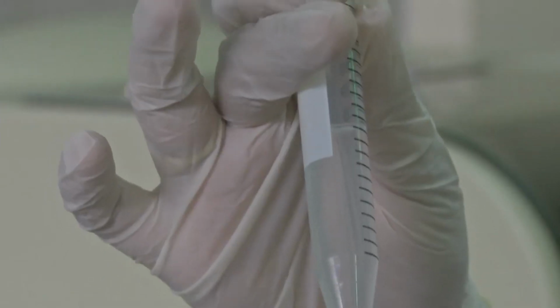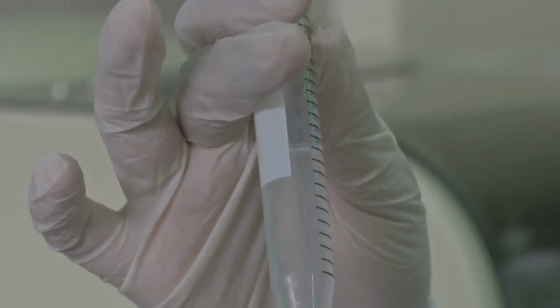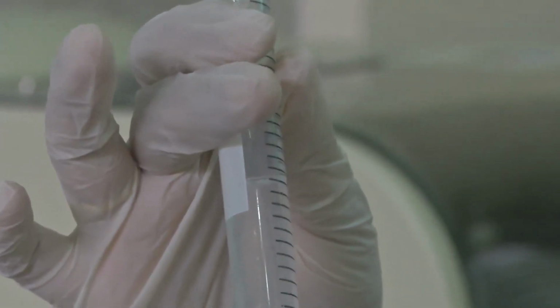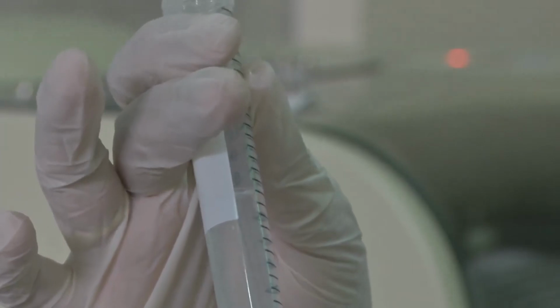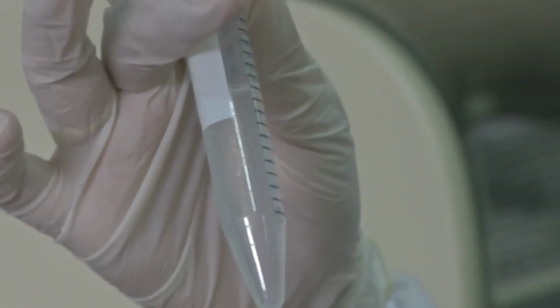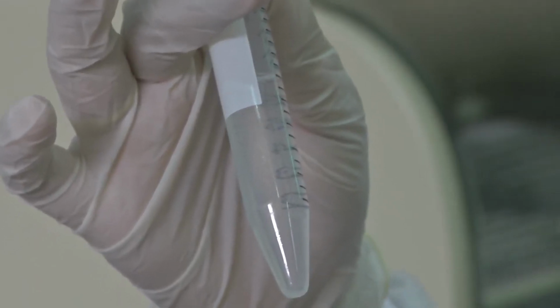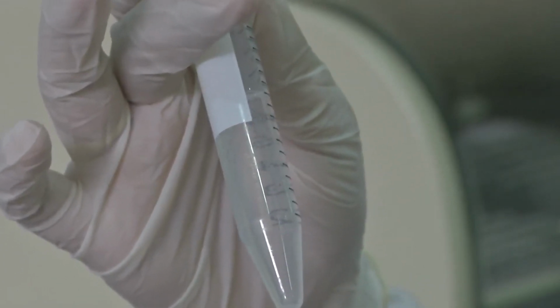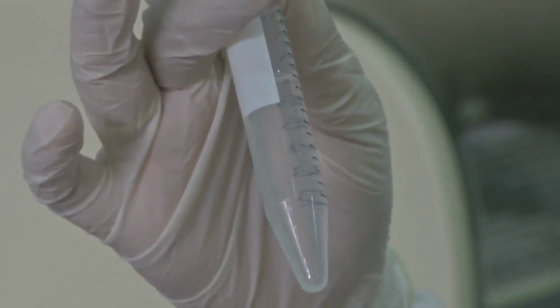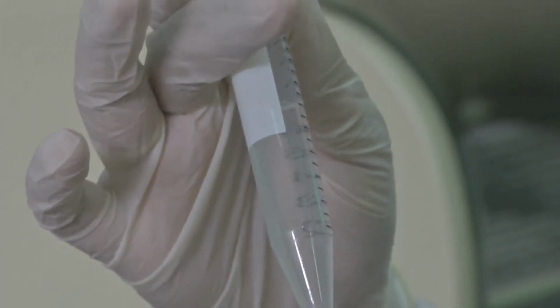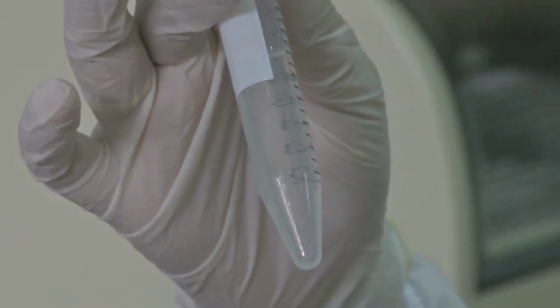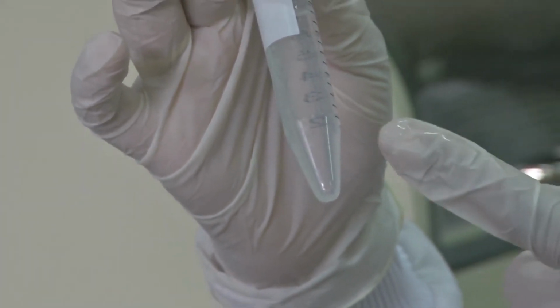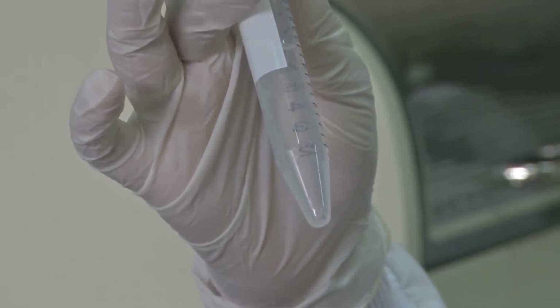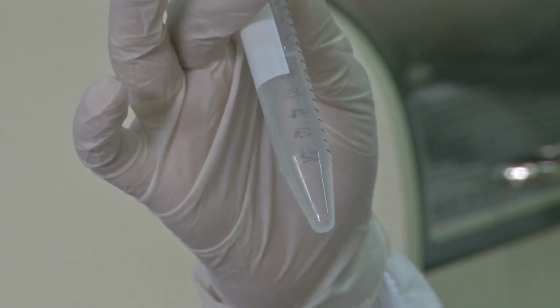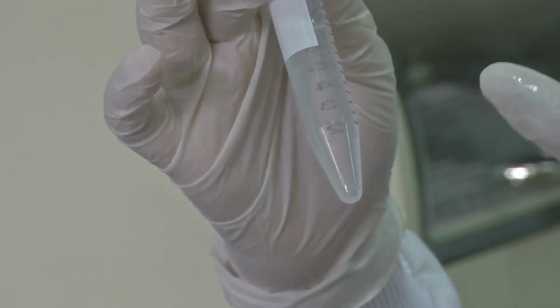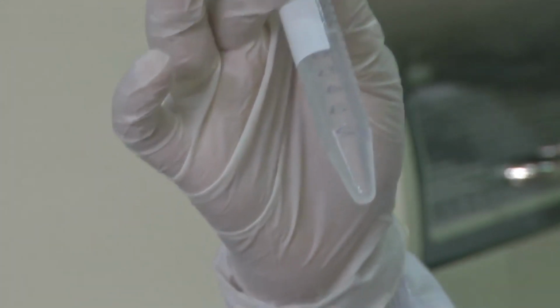If you see, there are a lot of air bubbles now which got formed while I was mixing the two polymers. We do not want these bubbles. You cannot use this mixture for curing, because we are talking about making biomems devices which have channels of a few micron length, and the dimensions are so small that even a droplet or even a bubble here can block your channel, and that is not what is desired. So, even the tiniest bubble has to be removed from this mixture.